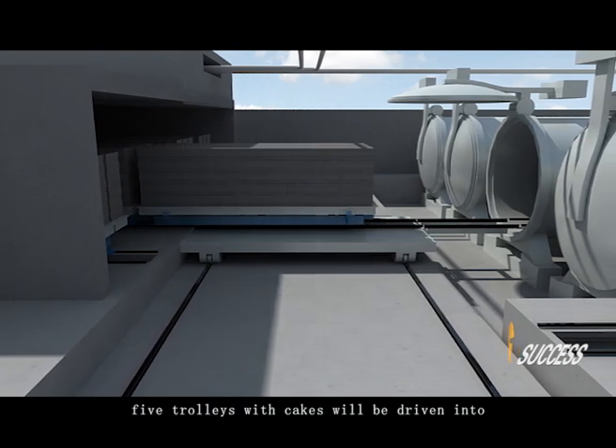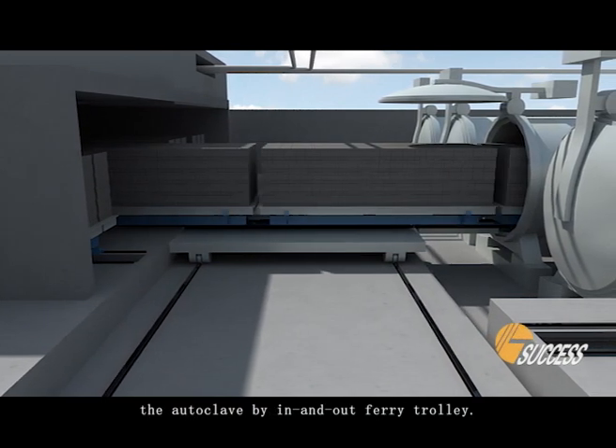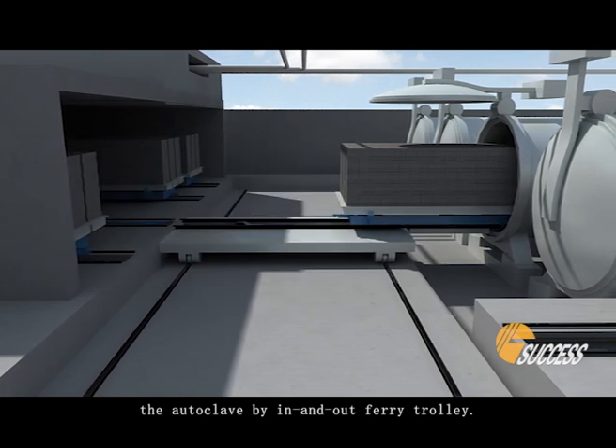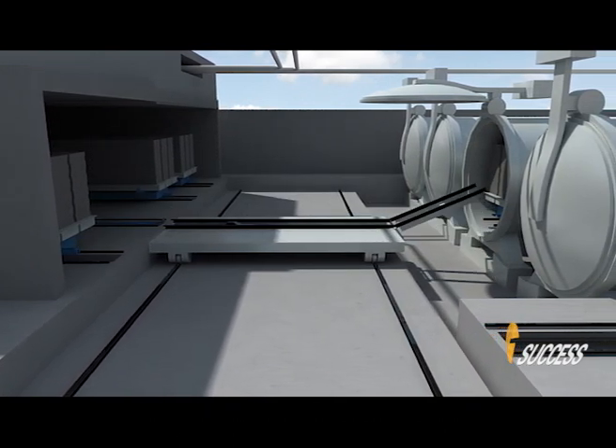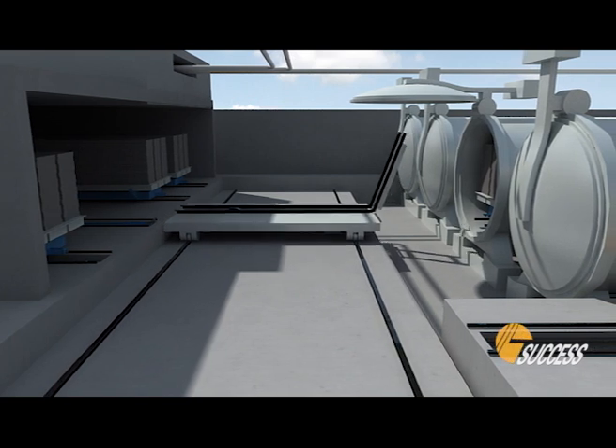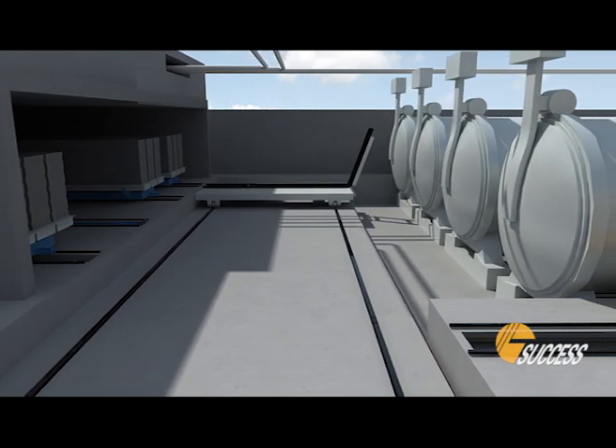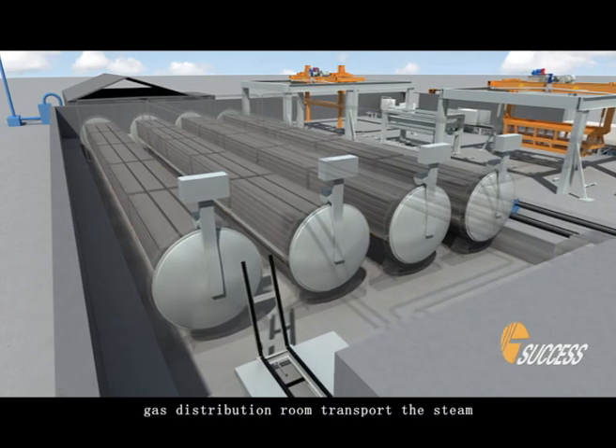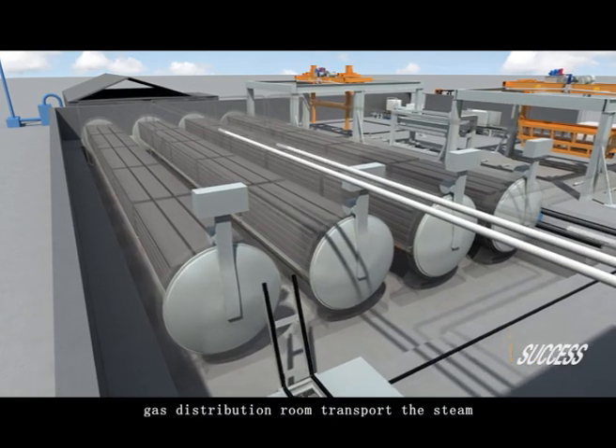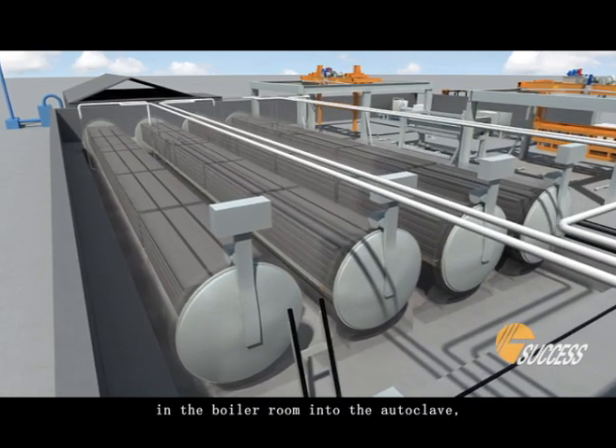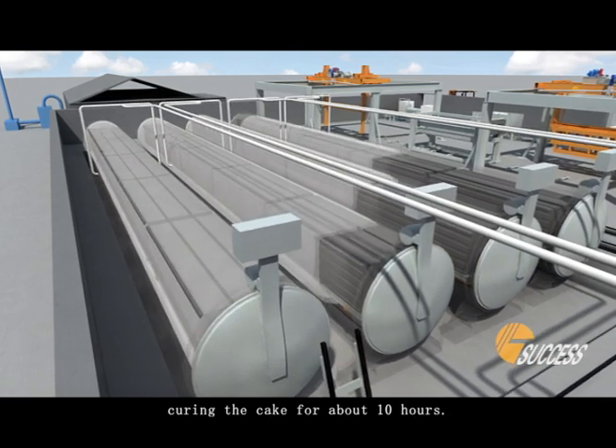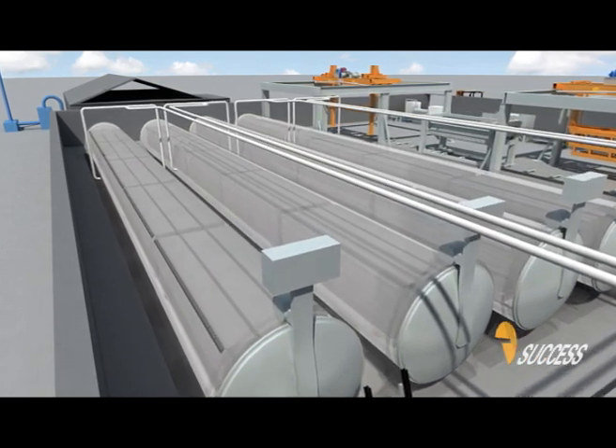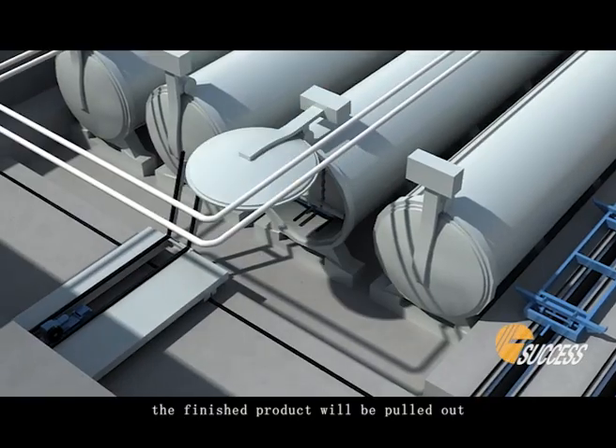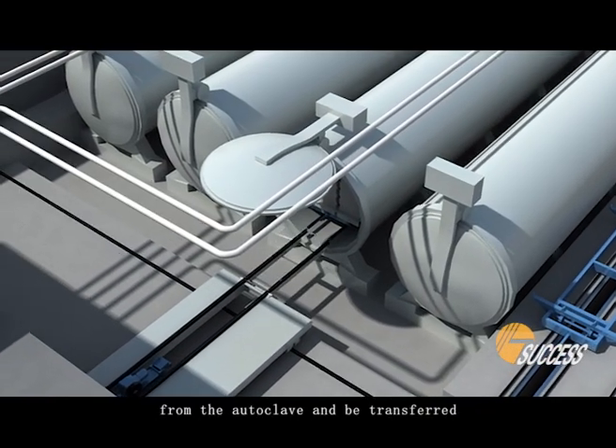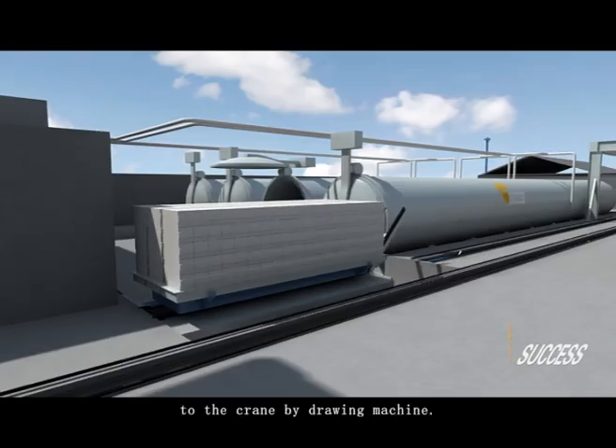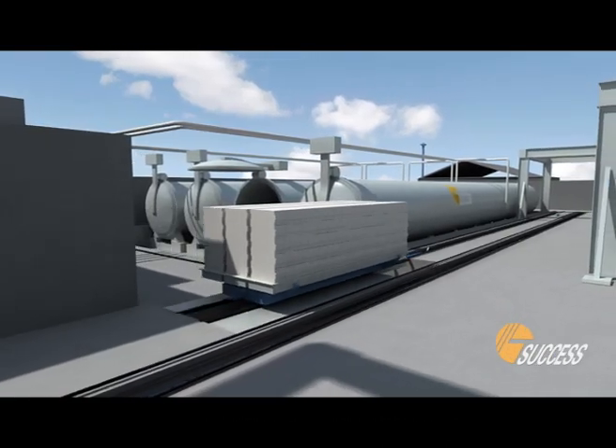Five trolleys with cakes will be driven into the autoclave by in-and-out ferry trolley. Gas distribution room transports the steam in the boiler room into the autoclave, curing the cake for about 10 hours. The finished product will be pulled out from the autoclave and be transferred to the crane by drawing machine.